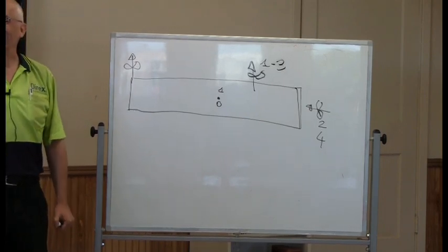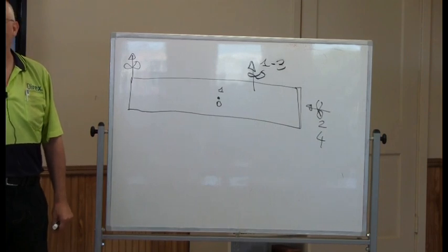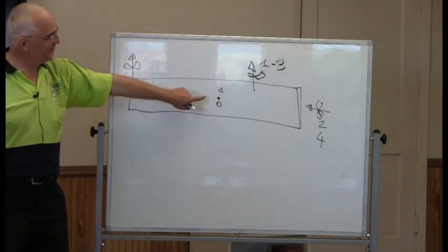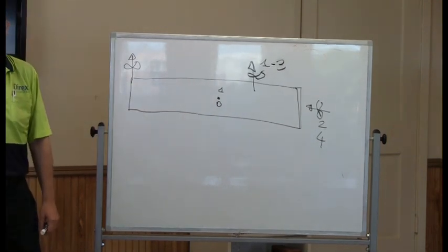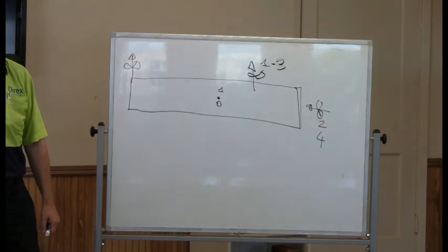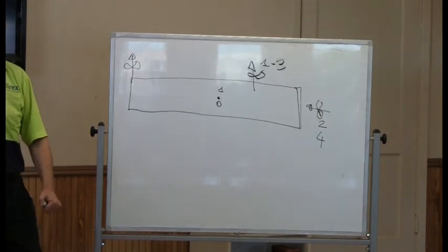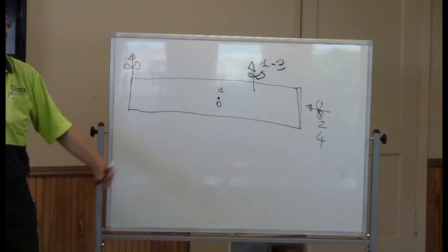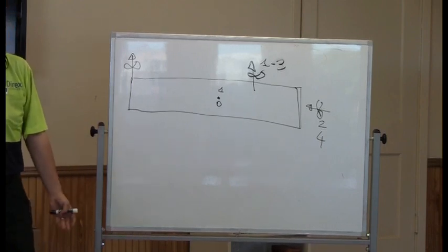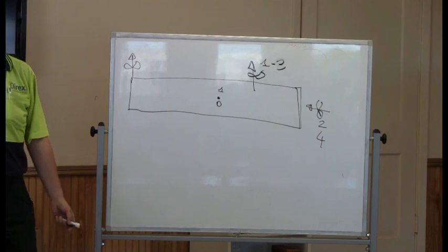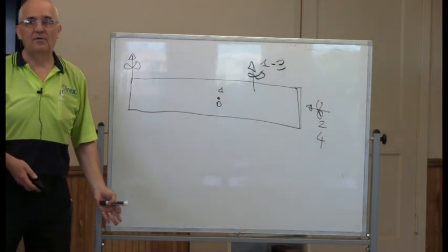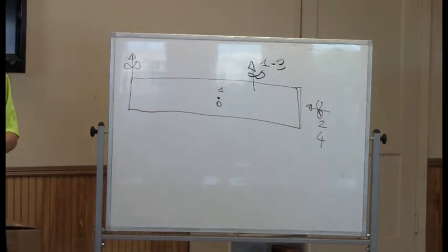Basically, you just took everything I know back here. And that was David, last week, David Mackey. He said, what is the pressure I need here? I said, I don't know, I don't care. If you have to remember one thing, forget about the pressure. The pressure is a consequence of flow. So we need to know the flow.